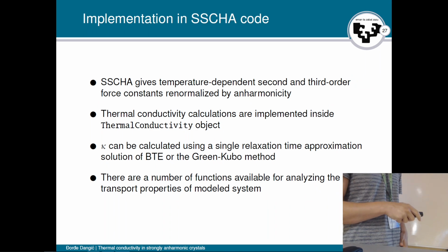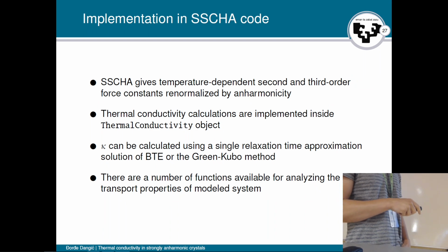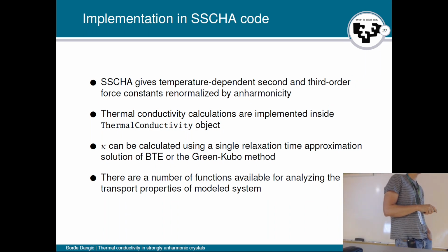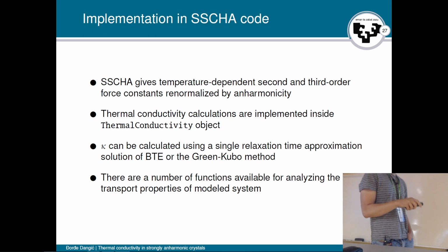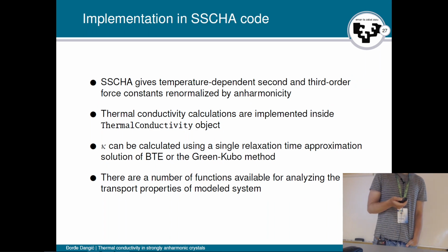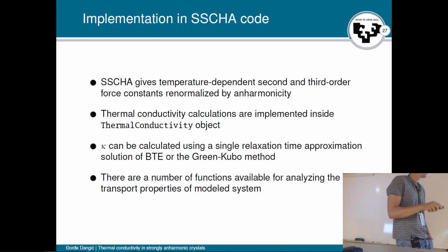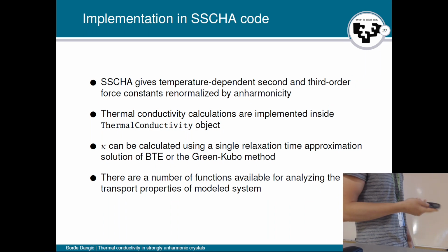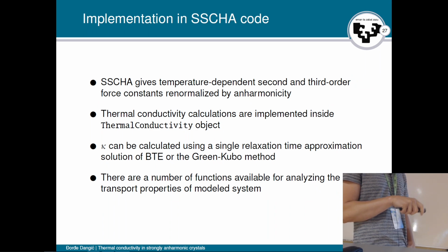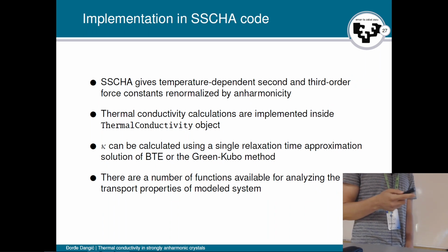The thermal conductivity calculations are implemented inside the thermal conductivity object in SSCHA. We can use the single relaxation time approximation solution of the Boltzmann transport equation or the Green-Kubo method to calculate lattice thermal conductivity. I guess if there is significant interest in this, we can improve these calculations by adding bells and whistles, but at this point we only have these two methods. And also there are obviously a number of functions that you can use to analyze the results. Again, this is something that hopefully will be guided by the user base and what they say is useful to them.